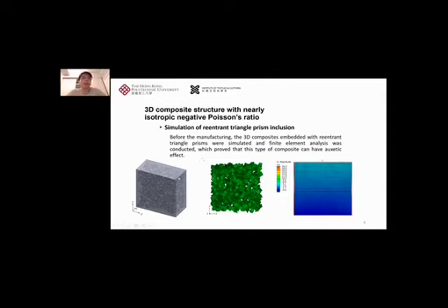So I made the inclusion with reentrant triangle cross section. If you look at the left figure, I made this model first. So I made this inclusion prism, having a reentrant triangle cross section and with a length of around 6 millimeter. Then we added around 400, 500, 600, 700 and 800 inclusions inside this matrix.